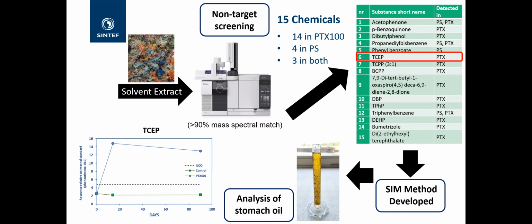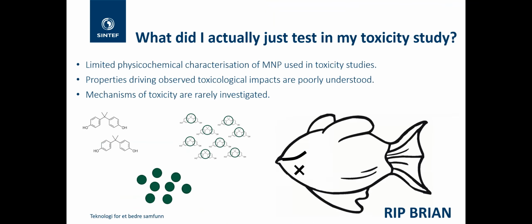It varied, not all of them were present in the stomach oil, but for certainly some of them we saw quite significant increases. So you've got the control sample in green, and then the blue line shows the concentration of this chemical TCEP in the stomach oil. So we were able to demonstrate that this, at least for certain species, is a viable exposure route.